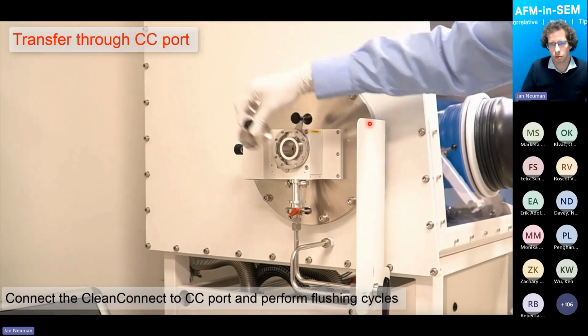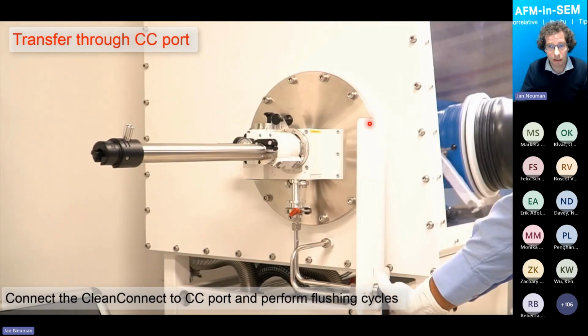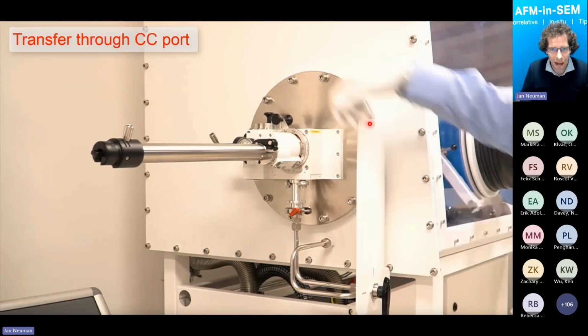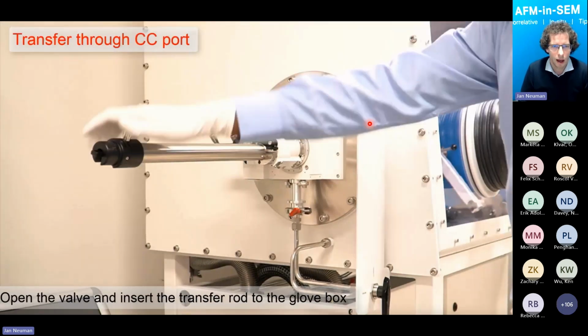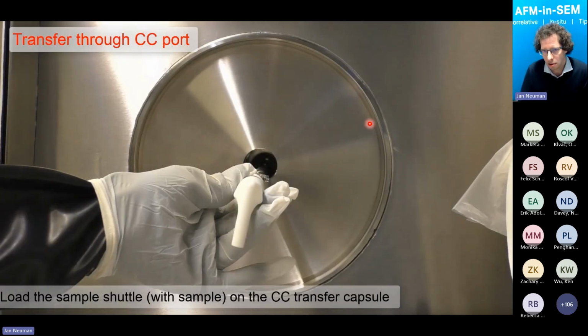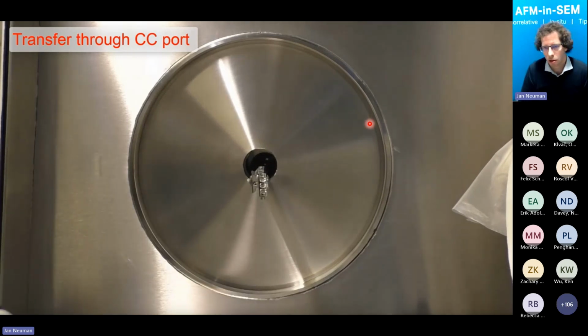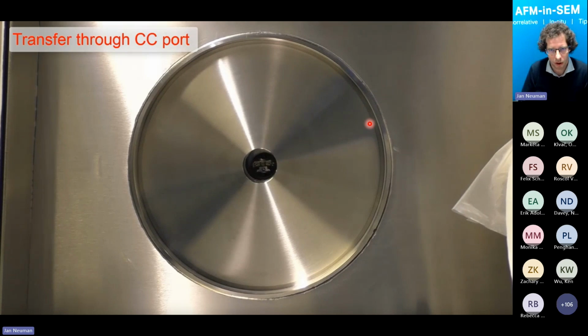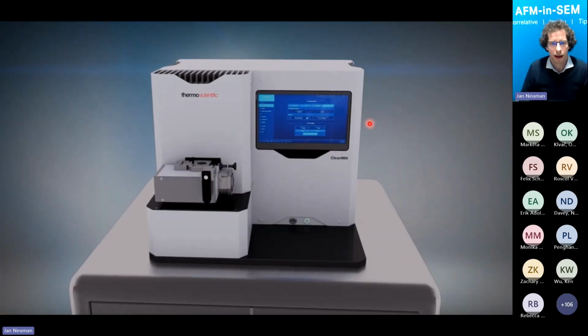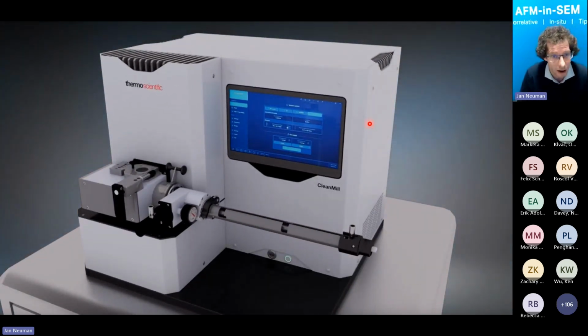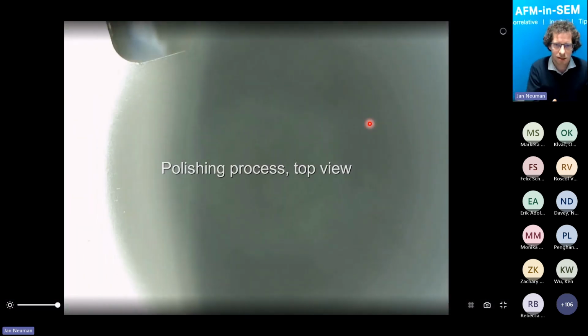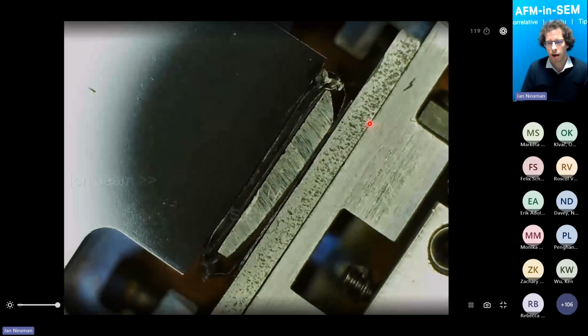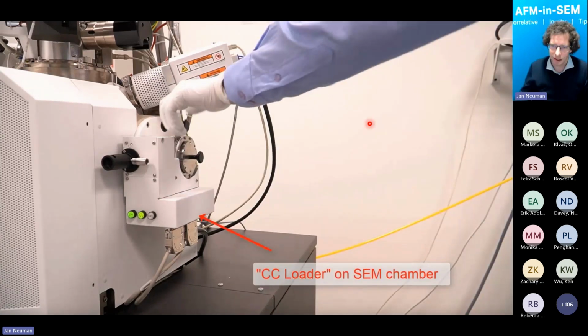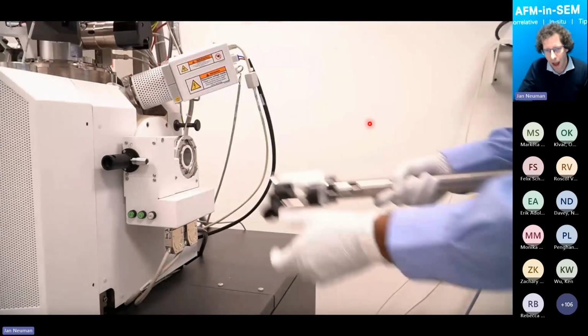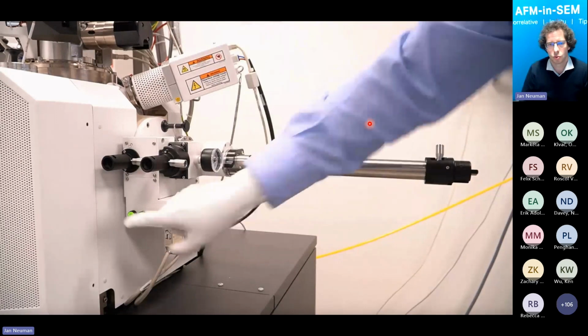So you have a glove box. On the side, you can open the port. You mount there the Clean Connect transfer chamber, which enables you to transfer the sample without any air exposure. It's quite straightforward. You just move in the sample holder, mount the sample holder to the rod, and put it into the transfer chamber in the Clean Connect. You close it and evacuate the transfer chamber. Now we are ready to take this into the broad ion beam milling, in this case the Clean Mill, where again the process is optimized so that no exposure is evident. In the broad ion milling, we take the sample and polish it with the broad ion beam, and after that, again, you can use a Clean Connect and bring the sample after the cross-section preparation into the electron microscope.